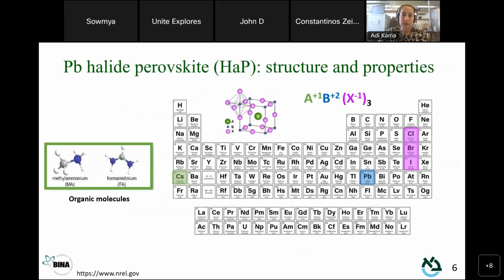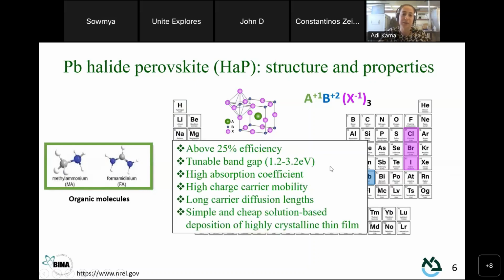So a little bit about halide perovskite. They have the formula ABX3, where X is the halide: chloride, bromide, or iodide. The A is a +1 cation: inorganic cesium, or organic molecules such as methylammonium and formamidinium. And on the B side, we have lead +2, which achieves the high efficiency we talked about. But not only that, it has a tunable band gap between 1.2 and 3.2 electron volts, a very high absorption coefficient for a very thin layer, high charge carrier mobility, and long diffusion length. And the most important thing is that those materials are cheap and simple to prepare.